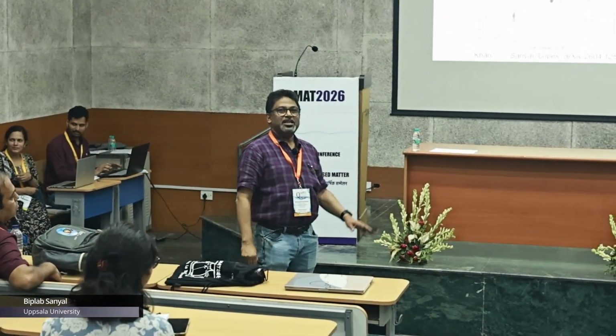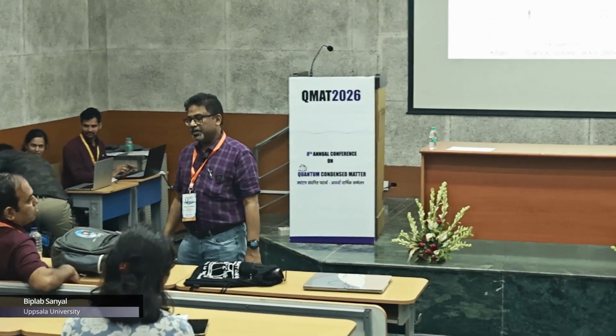Okay, it was a very good talk. Thank you. I just need one clarification. When you obtained the skyrmion, that was basically jacking up the DM interaction, right? Not only that, reducing the anisotropy also. Good, but you also mentioned that these systems are centrosymmetric. Centrosymmetric in the pure phase, like Fe3GeTe2, but once you start doping, then you break it. Even if you break it with oxygenation, you don't see skyrmions. Okay. So there must be something else happening in the actual real system. Good. Yeah.